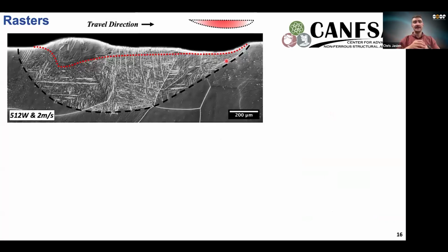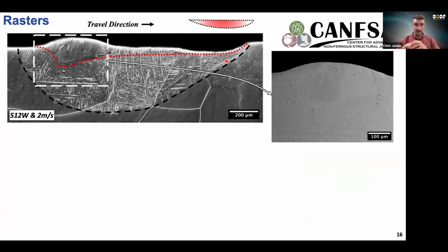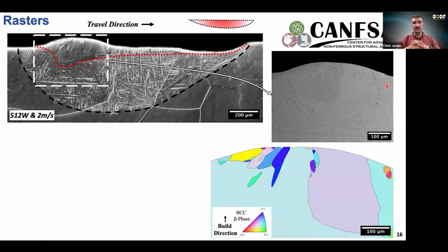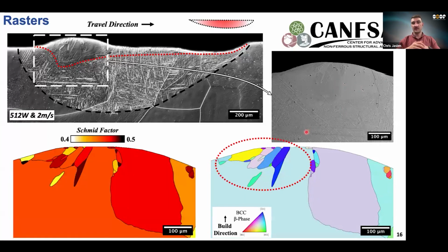And so as we go into another set of parameters, just to see if we're going to see the same things, we get a very similar response now with a higher power and faster travel speed as compared to the previous raster. As we investigate the first bit of the melt pool, as we did before, we see again a region of reduced transformation, and then abruptly there's a region of transformation. As we dive into it, we would expect that the Schmid factor would probably correlate to that.